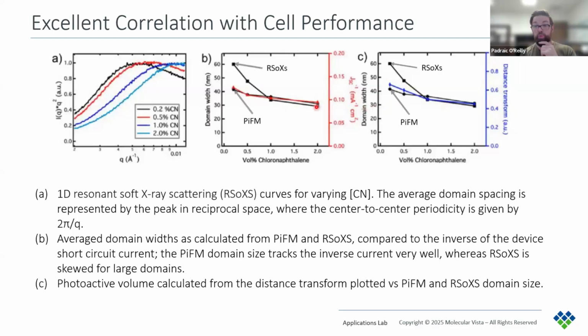We can see from the measured width, so this is the scale, the bar here on the left side, y-axis, that the domain size for PiFM tracks very well with the cell performance for both of these measurements. You can see the bottom black line here is PiFM. It tracks the red line here and the blue line here. Whereas for RSoXS, it diverges for the larger domains. So this is an example of PiFM being compared with results from another separate measurement technique and where it seems to perform better.